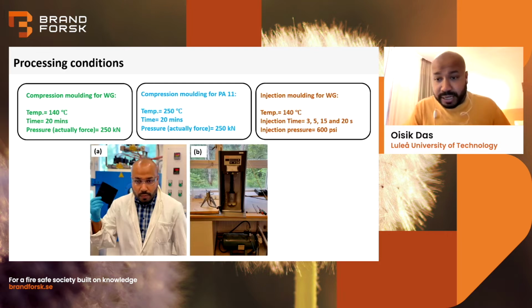And for injection molding, we use the same temperature as compression molding, 140. Injection times were 3, 5, 15, and 20 seconds, and the injection pressure was 600 psi. And these conditions were chosen after trial and error to find a sample that comes out cohesive and formable. And this is me holding one of the samples, and on the right hand side is the injection molding machine that we used.